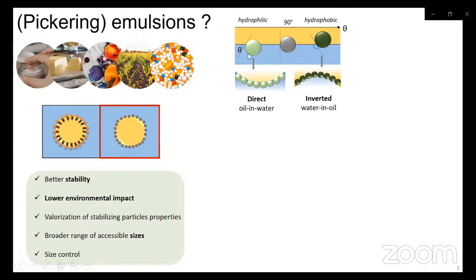These particles are very important to choose because their nature will impact the nature of the emulsion. If the particle is hydrophilic, which means it's wetted by the aqueous phase, it will lead to a direct emulsion, which is an oil droplet stabilized in an aqueous medium. On the contrary, if the particle is hydrophobic, wetted by the organic phase, then you will have an inverted emulsion, which is a water droplet stabilized in an organic medium. In our case, we are working with cellulose nanocrystals, which are not spherical particles, but anisotropic particles with a rod shape.